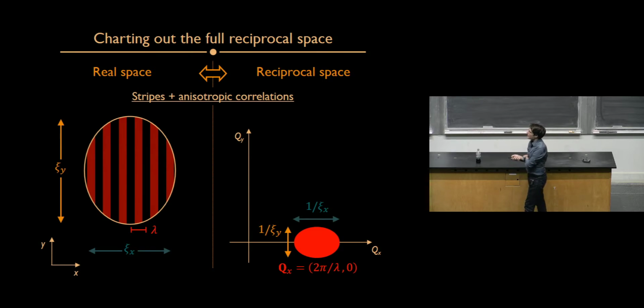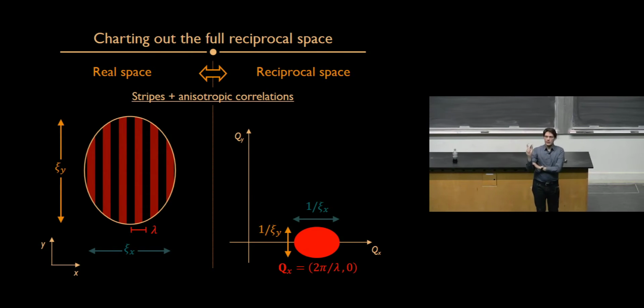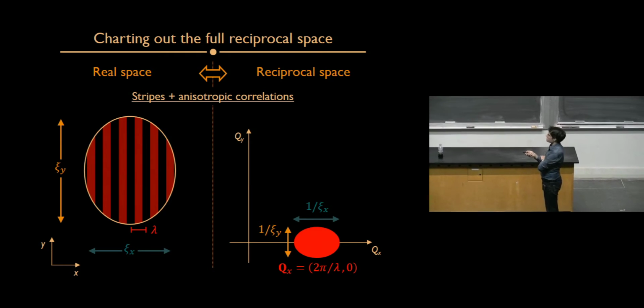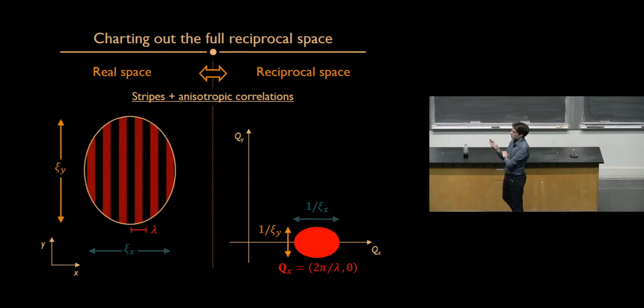And the broadening in reciprocal space is, as we know, inversely proportional to the coherence in real space. Okay, so if this is the coherence length along x and this is the coherence length along y, then the vertical broadening here is 1 over this coherence length and 1 over the coherence length along x for the broadening along qx. So now if I shrink this domain along the x direction, what happens is that because of this relationship between the momentum space and the real space coherence, this peak will become broader in the qx direction in reciprocal space, because the domain has become narrower in the x direction in real space.